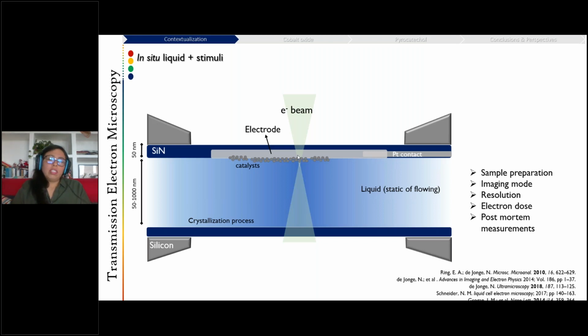But of course, there are challenges when we are inputting an electron beam within a liquid in an electrochemical media. So we had to answer several questions regarding how the sample should be prepared, which type of imaging mode we should use, how the resolution would be degraded with the amount of liquid we would put, which electron dose we should use to avoid any electron beam damage, and how to perform post-mortem analysis in samples that are not the typical ones. So most of my work during my PhD was precisely related to how to answer all those questions regarding the electrochemical TEM.